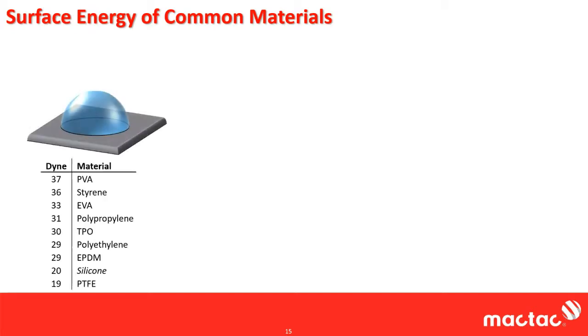Now looking here, we come to the cheat sheet that I mentioned, surface energy of common materials. This first column is going to be low surface energy materials. Again, your bead is sitting really high. You have what would be known as a high contact angle. That bead of adhesive just isn't flowing across the surface. Encompassing this, you have polyvinyl acetate, styrene, EVA, polypropylene, polyethylene, TPO, kind of a blend of the two, and EPDM. These are all your low surface energy materials. And how we measure this is known as a dyne. You don't need to know what a dyne is, but it's a unit of measurement that is tangible and quantifiable. Again, using a goniometer, we can determine the energy, and we use dynes to describe that.